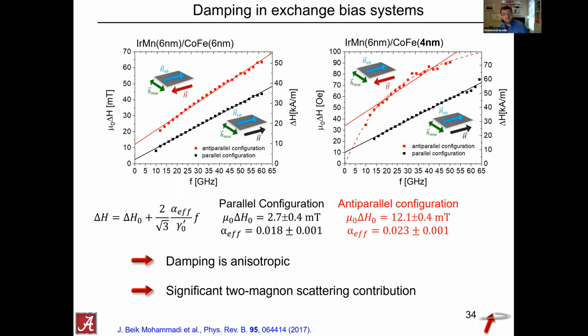The problem with two magnon scattering and the Gilbert damping term that's linear with frequency is you can try and fit a model that includes both. But what you end up with is a whole lot of fitting parameters that allow you to fit almost anything. So this is typically not a good way to really extract the underlying intrinsic damping. And so what we see here is at least the effective damping appears to be anisotropic. So the question is, where does that come from?